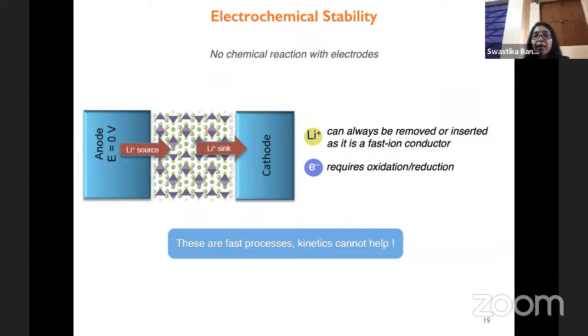It is when we combine the electrolyte with the electrodes, we basically have two drastically different electrochemical potentials at the two electrode sides. When you have the anode and the cathode, the lithium can act as the lithium source, and the cathode can act as the lithium sink. So you can have lithium ion redistribution at the electrode-electrolyte interface, and depending on the voltage applied, lithium can be removed or inserted from the conductor to the electrode, and that requires oxidation and reduction, which is not at all intended to make a stable device setup.